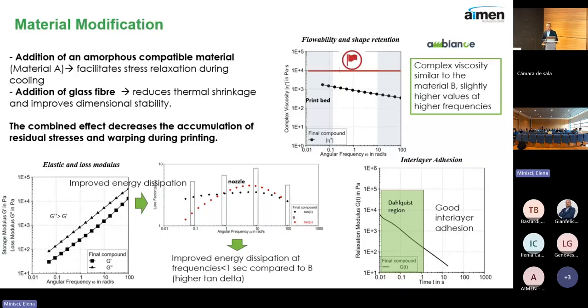So if you look at the picture on the top right, it's the complex viscosity curve. As you see, the curve follows a very nice trend. At high frequencies, we have low viscosity. Then when the frequency decreases, the viscosity goes higher. This is the so-called shear thinning effect, and this is precisely what we look for in 3D printing. At the high frequencies, we are